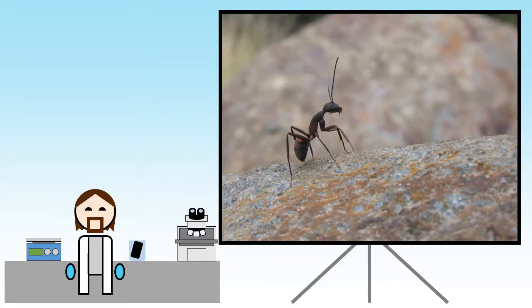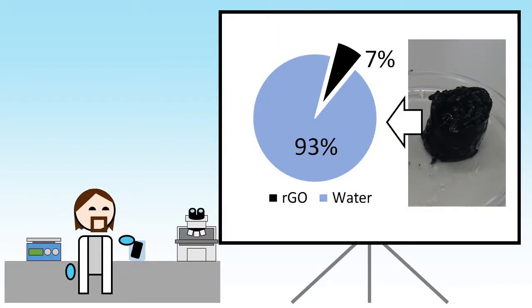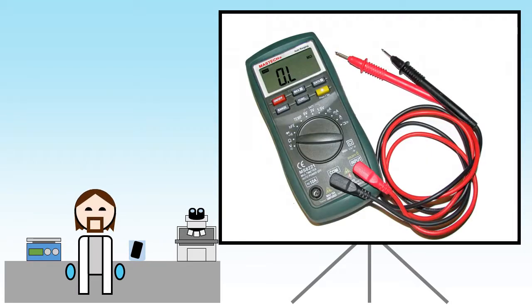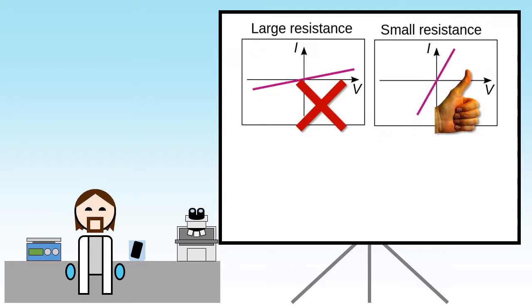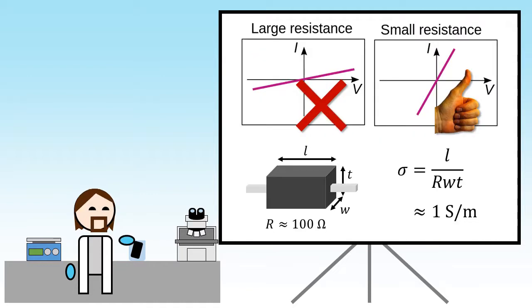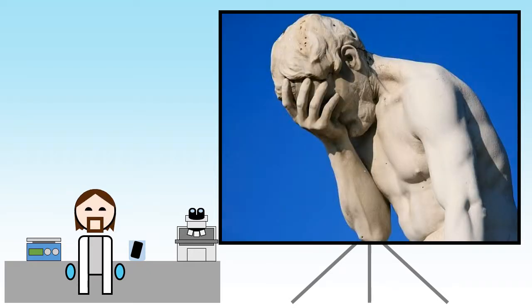It's a very, very small amount in this case. About 7% of the weight of this block is solid, the other 93% is water. If we poke the surface with the probes from the resistance meter, we find that our black mass is now very conductive. Crunching the numbers gives a conductivity of around 1 Siemens per meter. Doesn't sound all that impressive.